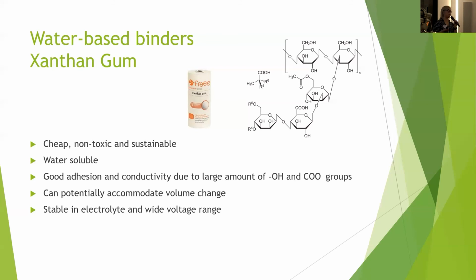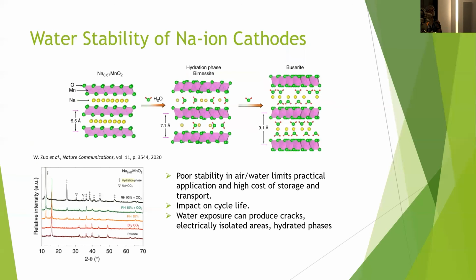Although one thing to point out, because it's water soluble, some sodium ion cathode materials aren't really water stable. They end up taking water in the sodium layers, as you can see in this diagram. So we have a sodium layer there. And when it's exposed to water or the ambient atmosphere, it takes up water and you end up forming this hydrated phase. And it basically has a really negative impact on performance. So it blocks conduction pathways for the sodium. And also because you get expansion of this structure in the C-axis, you can sometimes see cracks and areas get isolated from the rest of the material.